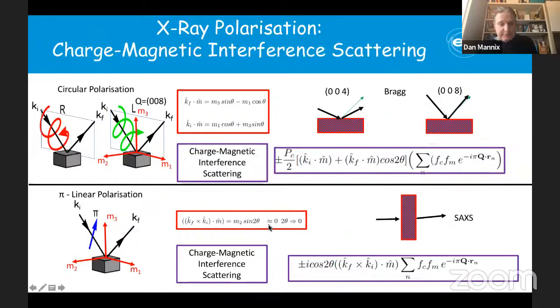This cross product term basically depends on the sine of 2 theta, the Bragg angle, and that gets very small, essentially negligible, as you go towards small angle scattering. So this kind of effect of seeing the moments out of plane can only really work in Bragg geometry, where you have high angles.